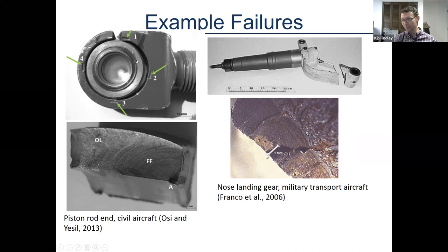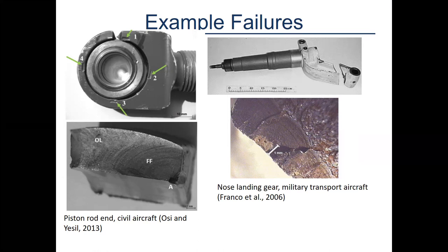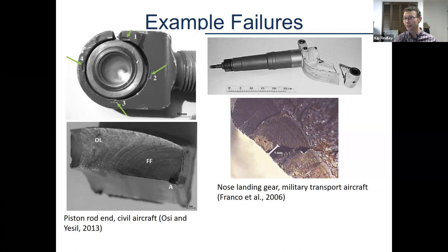What's really interesting about this one is that you see a little bit of paint here on the fracture surface. And so does anybody know what that implies? If we see paint right here on the fracture surface, what does that indicate? Does that mean that the part failed prior to being painted? Yeah. So paint seeped in? Yeah, exactly. So it means that there was a crack there when they painted the part already. And so that could have been a maintenance or replacement or something. Maybe it was a used part they just repainted, but there was already a crack there at some point when they painted it and put it back into service.